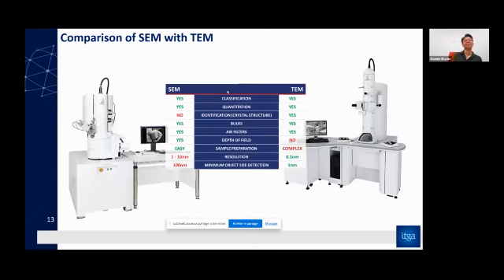Now comes the difference between SEM and TEM. These two are very similar in terms of what we can do with them. The advantage for SEM is that the sample preparation is easy, but the disadvantage remains in terms of resolution, because we can go down to a minimum size of only 100 nanometers. So if we have a very, very thin fiber, it might be easier with a TEM compared to an SEM.